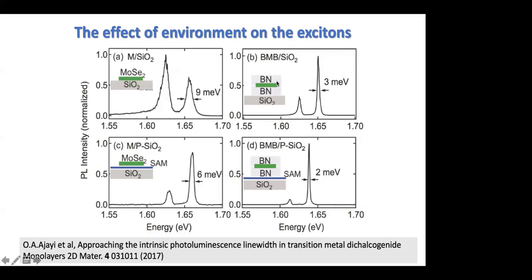How is it so? Boron nitride is very, I would say, stiff, very flat. And by putting the layer on this flat structure, it's like, you know, a carpet on the floor. If the floor is flat, the carpet will be also flat. And silicon oxide, I don't know if you tried or looked at the image of silicon oxide surface under AFM. It is very rough, resulting in this broadening of the features. So using boron nitride encapsulation, you can see the features with, say, 3 meV broadening. Just put on silicon oxide, it's 3 times bigger.